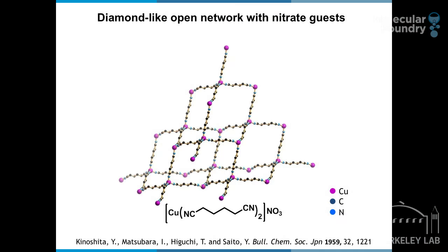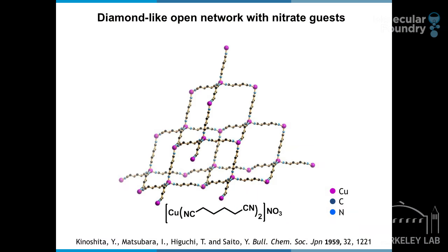But one can see from early literature back in 1959 some examples that this idea of building large structures from well-defined building units could be established. And that is the example of the copper-1 adiponitrile diamond structures shown here, with copper ions linked together by rod-like links, adiponitrile, to make a framework that is based on one of the densest structures known, and that is diamond, except here, because of the length of the units, the structure is open. In fact, in this particular case, the openness of the structure results in interpenetration, thus preventing the space from being accessible.